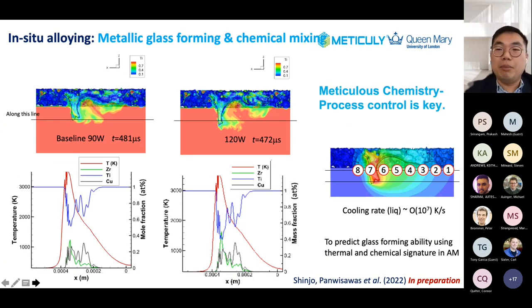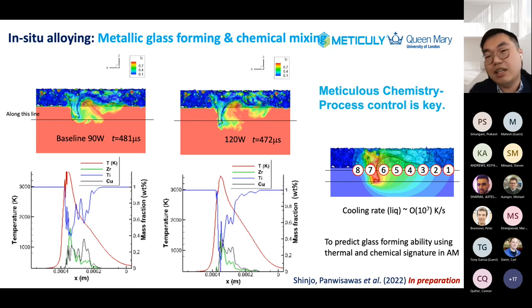So just to give you a bit of flavor of what we can do. We have to meticulously control chemistry and process. And here we have two representative process conditions that you will see from the chemistry map, as a result of this high-fidelity model, that are different if you vary the process condition. And this can be quantified and predicted if we use this model, and we can also link further to the solid-state transformation. If we get this right, your thermal signature will be right. And not only that, the trend after this is the chemical signature. We need to get it right as well for additive manufacturing.